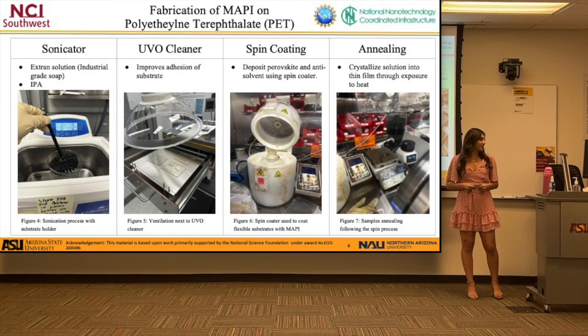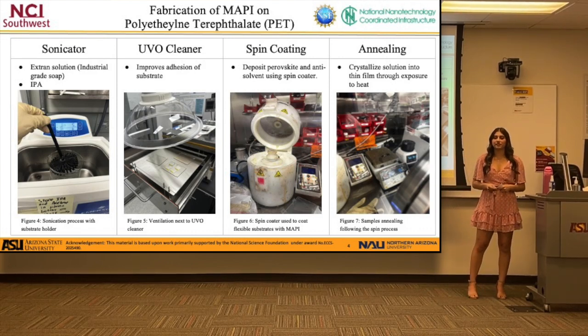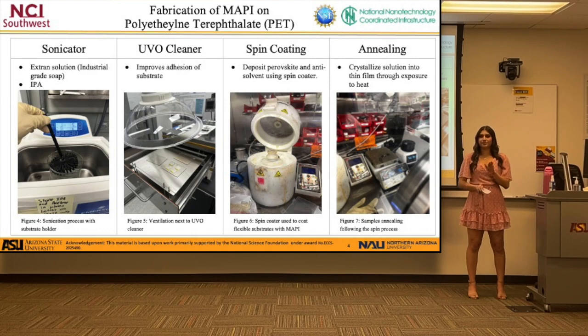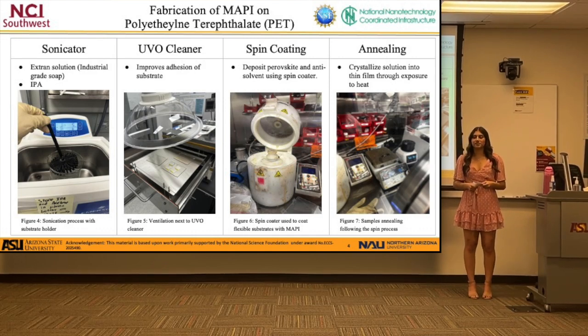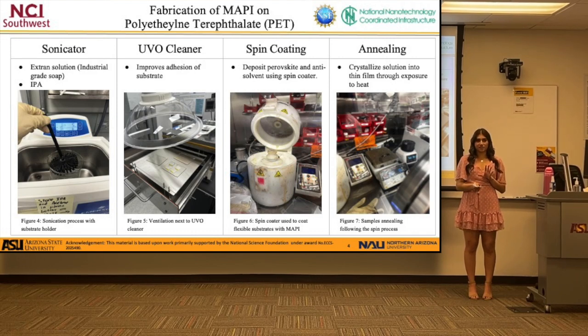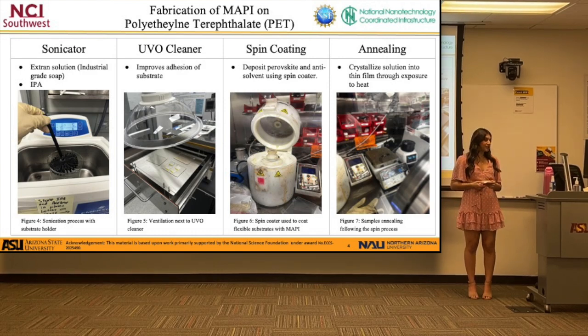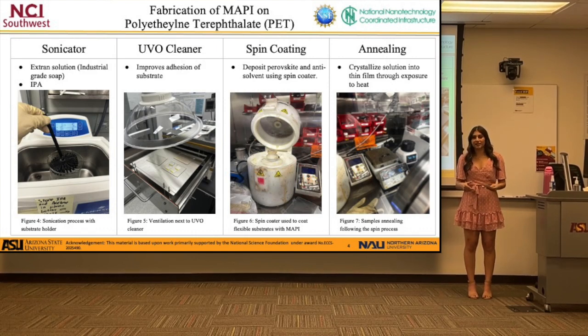The next step in this process is using the UVO cleaner. Through putting substrates in this UVO cleaner, it uses a combination of UV and ozone to prepare the sample to allow the perovskite to adhere to it better. And this is essential for the next step in this process, which is spin coating. So this is just the step where I deposit the perovskite and the anti-solvent on the substrate itself.